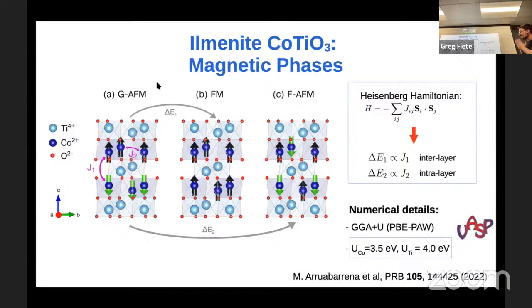We do this in the following way. We use DFT calculations, as well as some model Hamiltonians, which let us describe the magnetic couplings of the system in a quite simple way. Let's think about it. Here, you can see how this compound, well, we studied several magnetic configurations, but we reduced the fundamental magnetism of this compound to the presence of two magnetic couplings, J1, the interlayer magnetic coupling, and J2, the in-layer magnetic coupling. By means of DFT calculations, we can compute the total energy of each one of the different